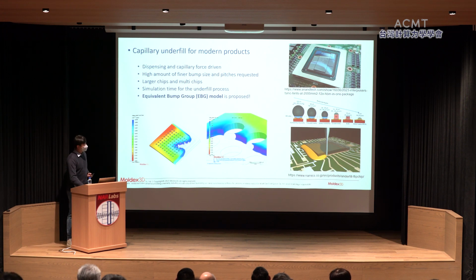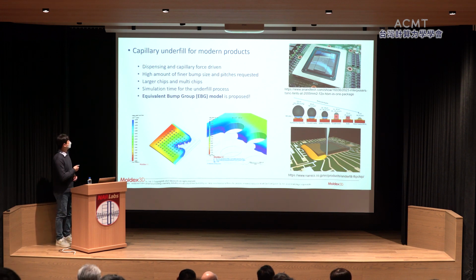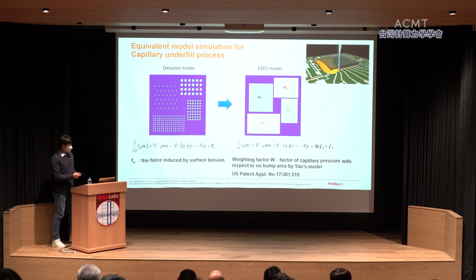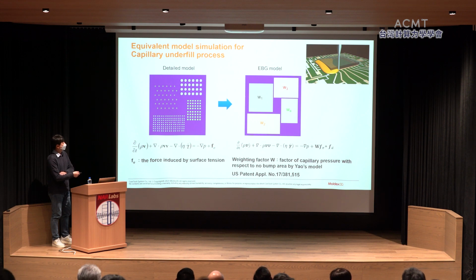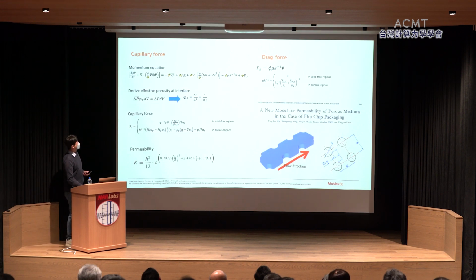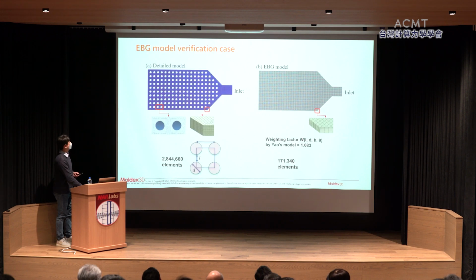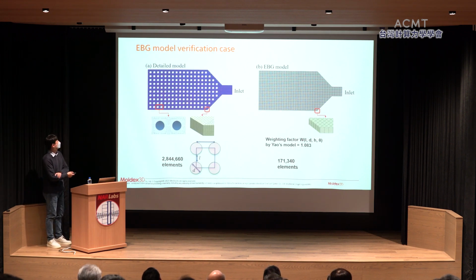Therefore, we are trying to introduce an equivalent model. We call it the equivalent bump group model. In this model, we treat these areas with solder bumps as porous media, and find the weighting factor to use to simulate the capillary pressure with different bump density. And these are the formulations. I'll skip this.